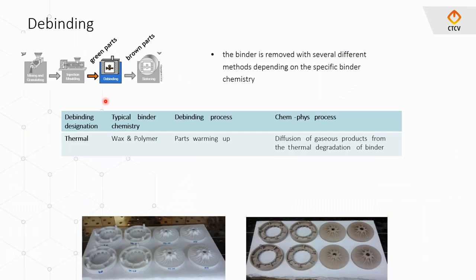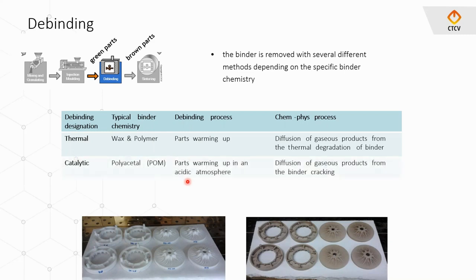So the next step of the process is debinding, where the binder is removed by several different methods depending on the specific binder's chemistry. So I will present the common methods to remove the binders. There are some binders composed of wax and polymers that can be removed by a thermal way, where the parts are warmed up until the polymers start to degrade thermally.